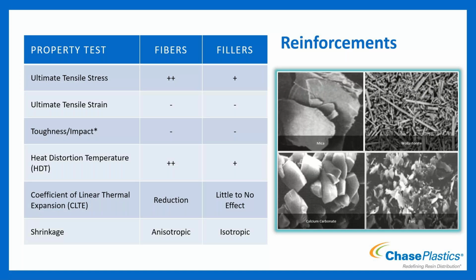I say typically because it depends. If it's a really brittle material to start with and you add glass fibers, you'll actually see an increase in impact performance because the glass kind of takes over. But if you take a really impact resistant material like polycarbonate and add glass to it, you're going to see a decrease in impact performance. So there's kind of an asterisk there.